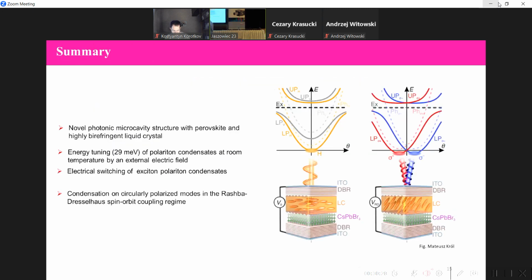Just to sum up my presentation, we obtained a novel photonic microcavity structure with perovskite and highly birefringent liquid crystal. In this structure, we can have energy tuning of polariton condensates at room temperature by external electric field. There is also electrical switching of exciton polariton condensates, and condensation can be on circularly polarized modes due to Rashba-Dresselhaus spin orbit coupling.